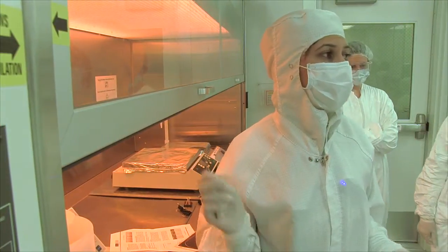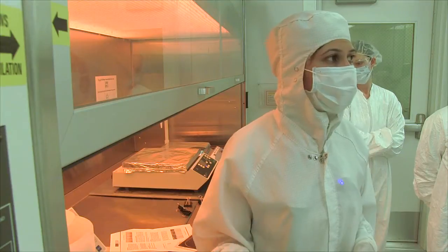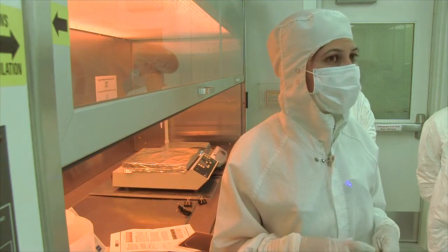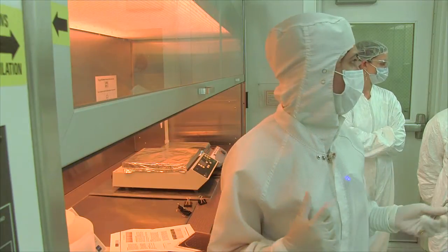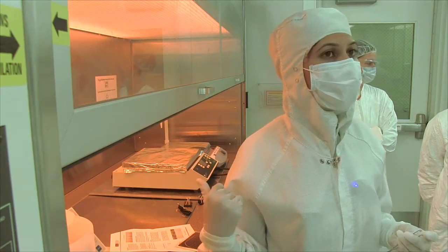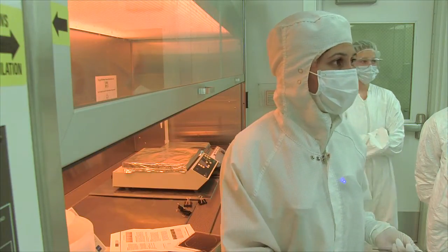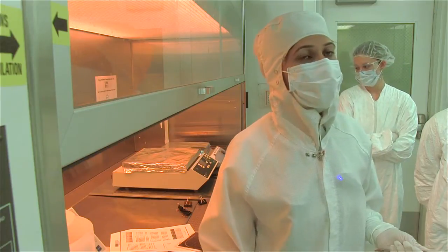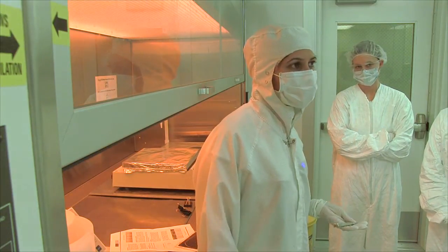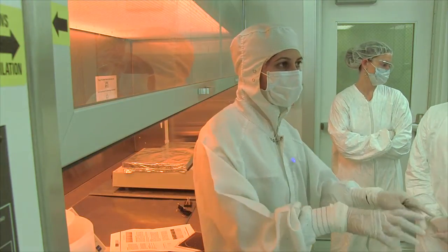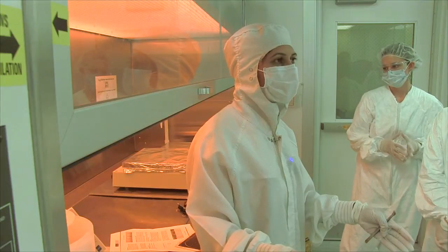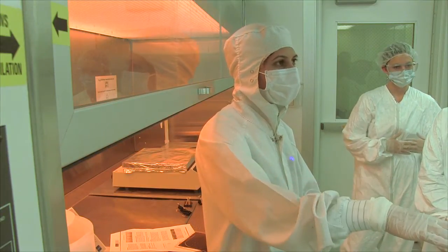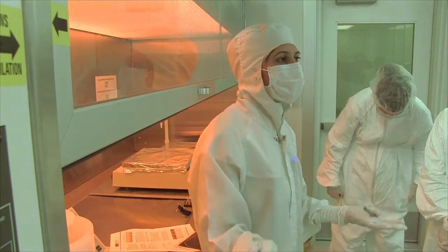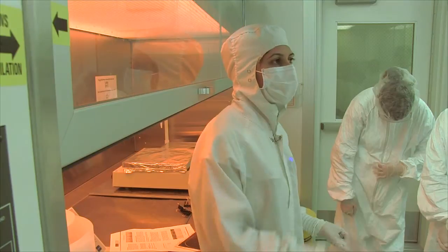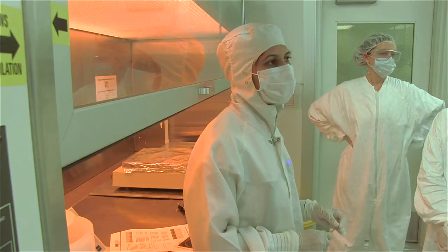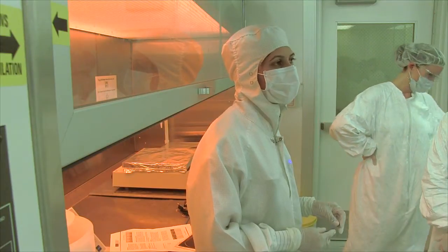But in this case you are actually cross-linking it, because what the UV light has done is initiated the photoinitiators in SU8, and now they will act as a catalyst and do the cross-linking. That is done during the post-exposure bake, and that was a question also in the exam. So we don't do post-exposure bake for some photoresists, especially positive photoresist, because in that case we are degrading the area which is exposed to the UV light. So we have some polymer and a certain area is degraded, and then we are washing that away. So we don't really need to cross-link anything. And this step is done for cross-linking. So it's only done mostly in the case of epoxy-based negative photoresist.